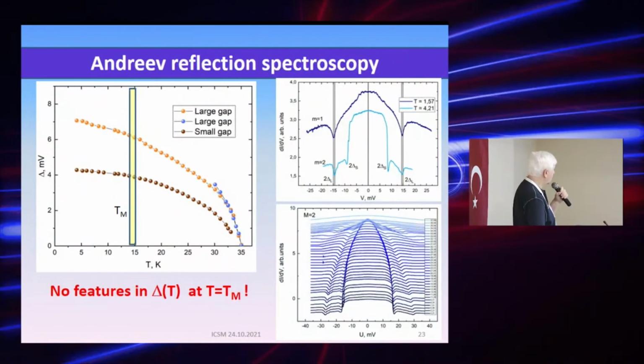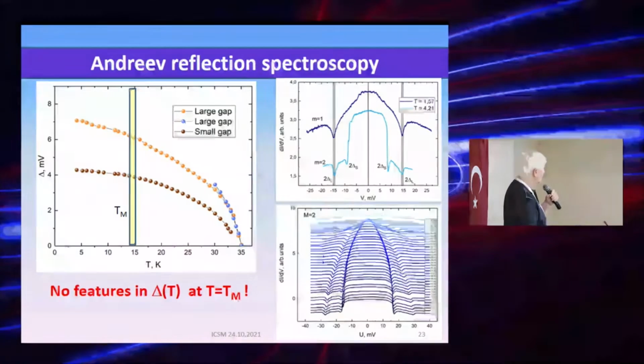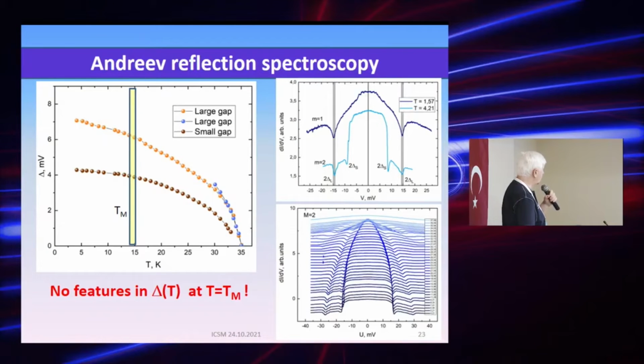And actually the reason why we see only 2 gaps is that Andreev reflection spectroscopy is momentum averaged. So after some thinking and processing, we can identify these 2 gaps as a combination of those 4 gaps which can be seen in ARPES. In some measurements we saw 3 gaps, but I don't have detailed data to show the full development. Nevertheless, in total they are consistent with ARPES, but again the main conclusion is that we do not observe any deviation from smooth behavior at the magnetic transition temperature.